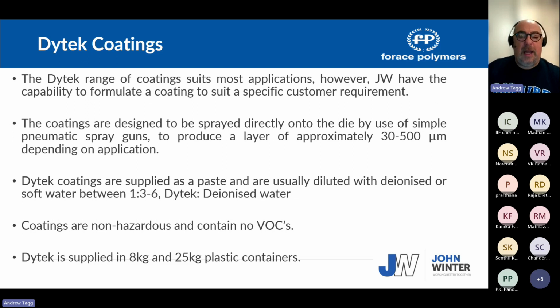In the special cases of automotive wheels, four-wheelers produced by GDCs, the coatings can get up as thick as 800 microns, and I'll talk about that later. The coatings are supplied as a thick liquid or a paste, and they're usually diluted down with deionized water or soft water. It's interesting.